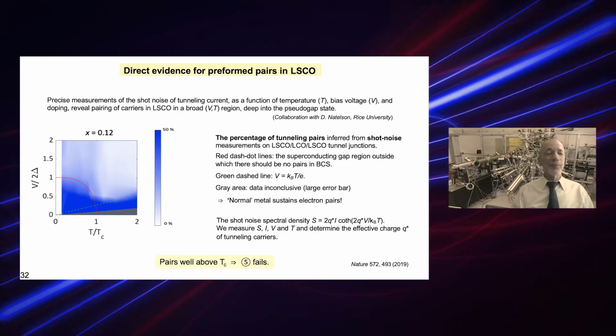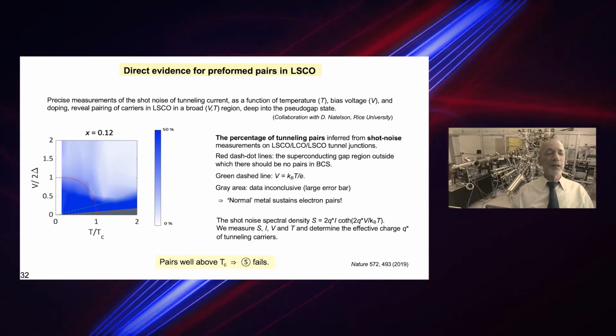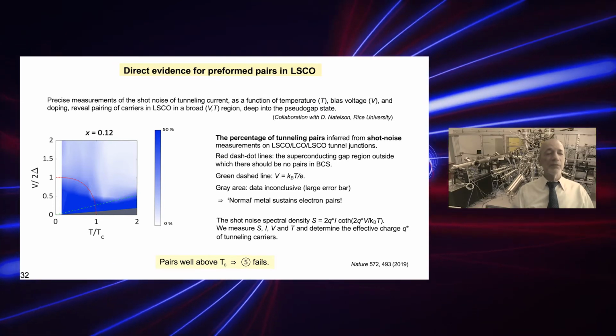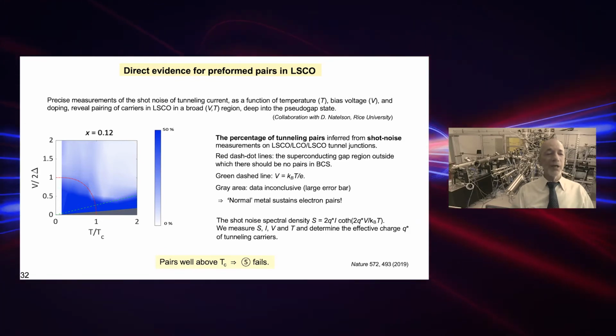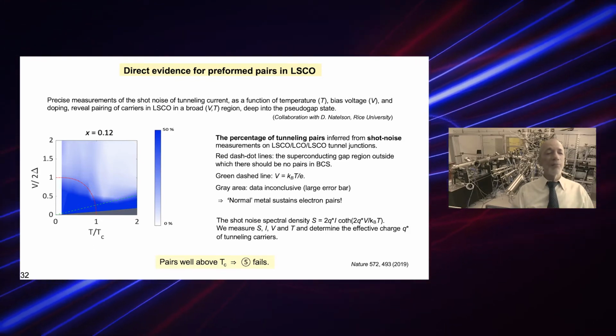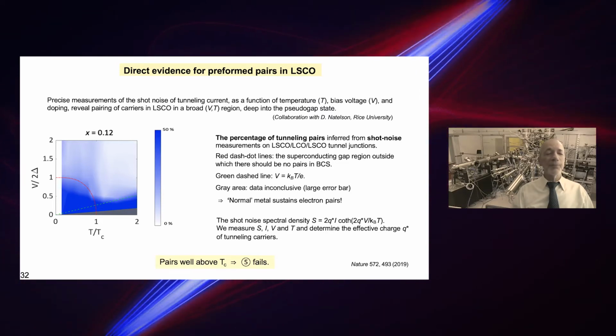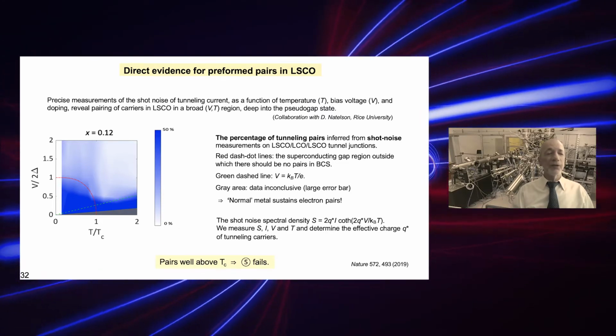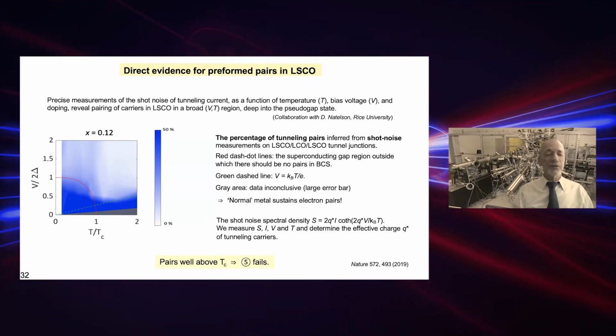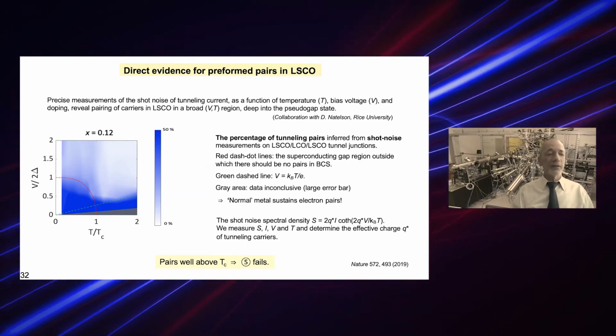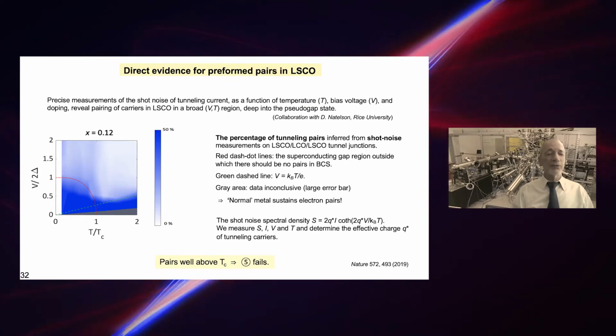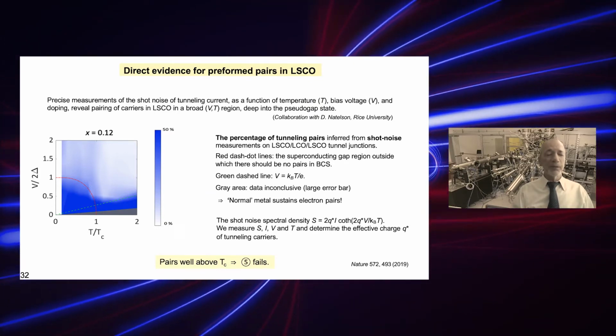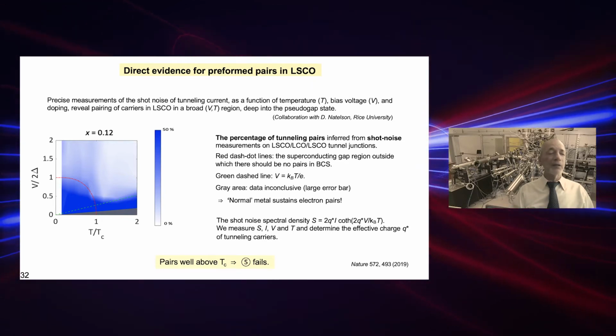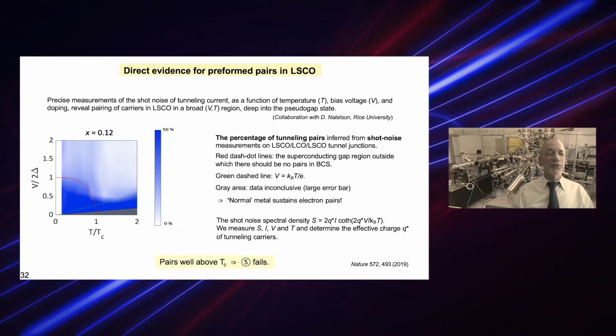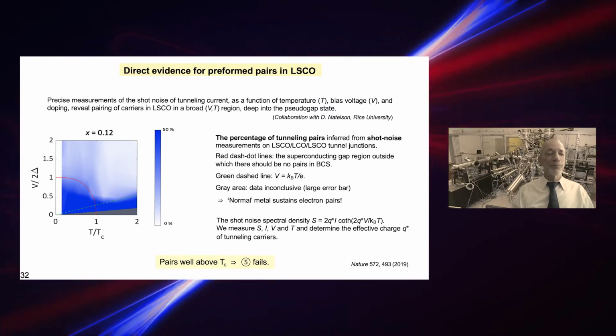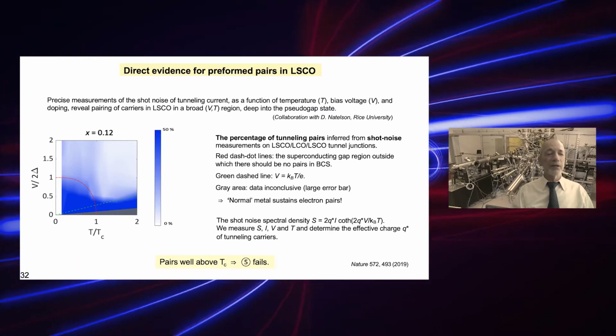The red line shows the superconducting gap region. We see that a large fraction of electrons is paired even way outside of this region, along both axes, not only well above TC, but even above twice the superconducting gap energy. This is quite shocking. In the normal state, a substantial fraction of charge carriers is paired, therefore bosonic. It looks like a new state of condensed matter. Some people call this emergent Bose metal. This finding indeed strongly constrains the theory and may prove to be pivotal to cracking the high TC enigma.